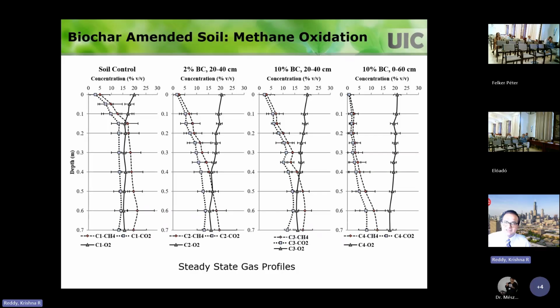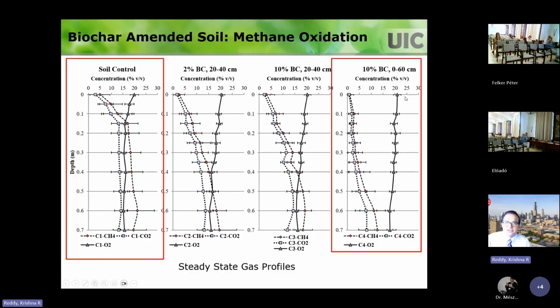But you need to do column experiments. As I said, column experiments are the ones that simulate the landfill cover and the gas transport through it. So we did a lot of tests. With the soil control, you do with the soil alone. And then we did with a 2% biochar layer, a 10% biochar layer, or 10% biochar added to the entire column. So if you do the soil versus, let's say, 10% biochar, if you look at the concentration profiles of methane and CO2, there is not much change.